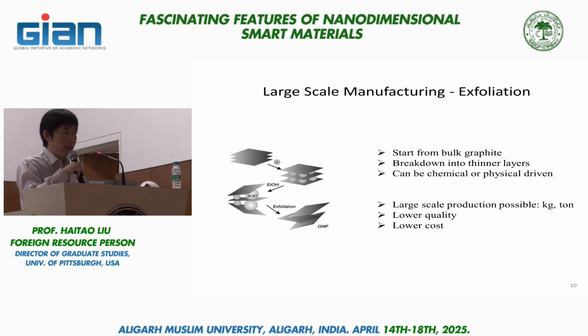There's also a lot of research done in so-called graphene oxide material. This is the case where you chemically oxidize graphene, installing oxygen functional groups, and that makes it amenable to essentially exfoliation in water because the whole material becomes much more hydrophilic. I'll talk more about this on the cover material side. But what I think is the most interesting, probably most impactful, is the so-called direct mechanical exfoliation approach.